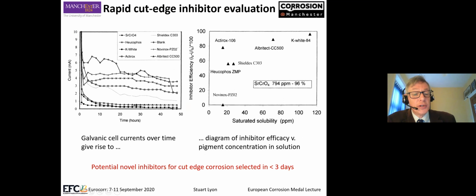Here is the current flowing in that system. Lots and lots of different inhibitors. I'm not saying these are good or bad. I'm just saying these are the ones we happen to have in the cupboard at the time. Some are not very good. Some are extremely good. Chromate is off the top of the scale. But you can see that, by analysis of the galvanic current decay over time and the final current, we can create a diagram of inhibitor efficiency versus pigment concentration in solution.